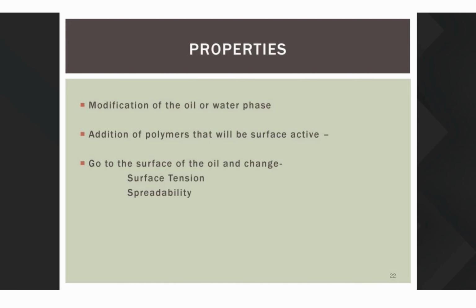Now, I don't think I can overemphasize, for people who are in the lab, the desirability of testing surface tension. Like I said, small changes people pick up quickly. And when you can lower the surface tension, you're getting your material to the interface where its performance is most critical. If it stays in solution, you really minimize the performance, or you need a lot more material. So a fully water-soluble PEG dimethicone really gives very little in terms of substantivity or conditioning.